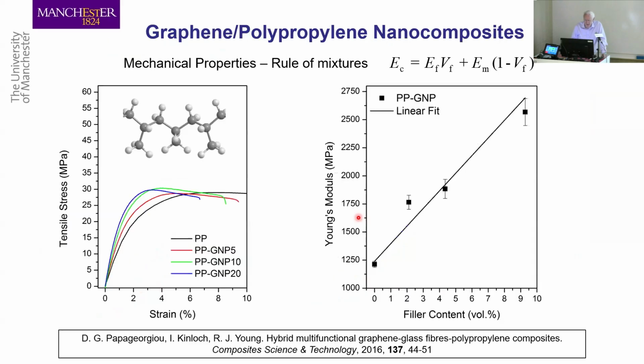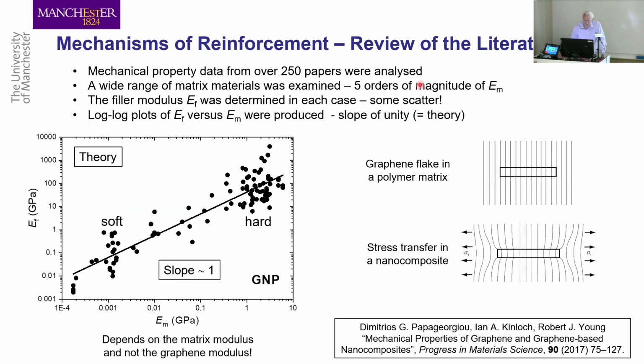Let's look at another polymer. This is polypropylene. This is a stiffer polymer. We put graphene into it, get the stress strain curves. We work out the modulus here, and in this case, we get a slope of 15 gigapascals. So we're into the gigapascal region now, but still, using the rule of mixtures, still below the 1,000 that we expected. And we've done this for lots of materials.